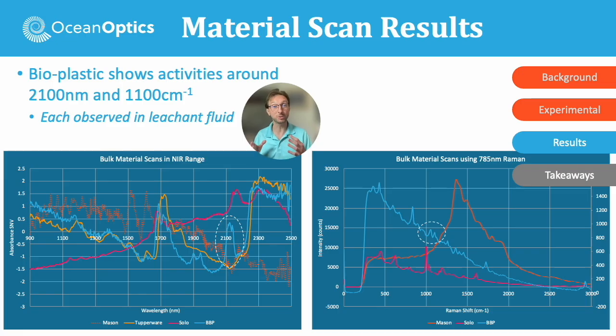And as we mentioned, we also scanned the bulk materials. We also scanned just the cups and Tupperware themselves with the UV, NIR, Raman, and all that to see if there were any correlative peaks. And for the most part, there weren't, except the bioplastic had two big clear synchronizations between those. So we saw in the leachant fluid the 2100 nanometer peak in the NIR, which we also see in the bulk bioplastic cup right there. And we also saw that 1100 wave number Raman peak when we did that Raman scan, and that's showing up likewise when we scan the bulk cup. So these are things that are very confirmable. We see it in the cup, we see it in the fluid itself.